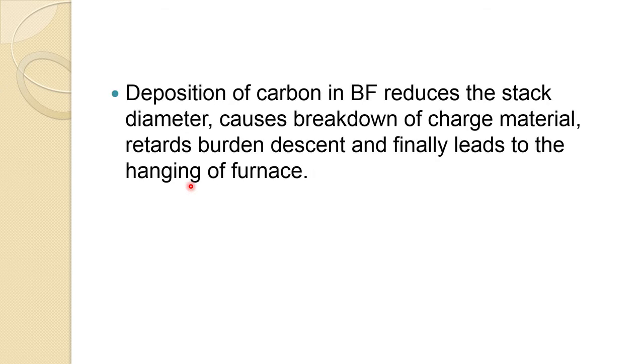It has many disadvantages, besides some advantage, but mostly disadvantage. Deposition of carbon in the blast furnace reduces the stack diameter. It deposits, and so the diameter of the stack is decreased as more mass is added. That causes breakdown of charge material, also retards burden descent, and finally leads to hanging of the furnace. So these are the major problems which occur due to the deposition of carbon, and one has to be careful and design the blast furnace reaction or the temperature zone so that it is minimized. One cannot completely get rid of this, but it should be minimized.